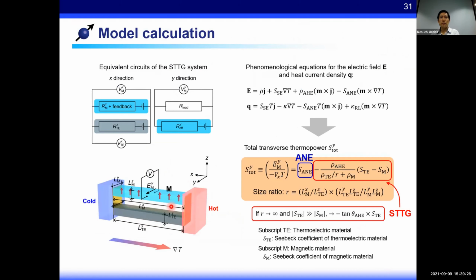The left figure shows an equivalent circuit of the hybrid material comprising thermoelectric and magnetic materials in the direction parallel and perpendicular to the temperature gradient. We phenomenologically formulated the transverse thermal power in this system and obtained this equation. The total thermal power is expressed as the summation of the anomalous Nernst coefficient and the STTG contribution. The STTG term strongly depends on the factor called the size ratio defined here, which is determined by the dimensions of the thermoelectric and magnetic materials. When the size ratio is very large, the STTG term is proportional to the anomalous Hall angle in the magnetic material and the Seebeck coefficient in the thermoelectric layer.